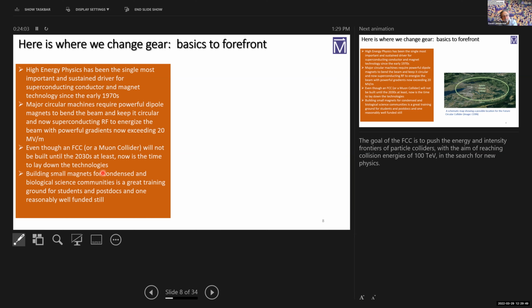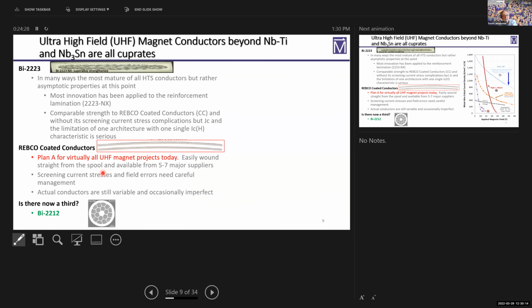And these magnets go up to 41 Tesla now as purely resistive magnets. And with a hybrid magnet of 11 Tesla of niobium-tin and 34 Tesla of copper, you get to 45.5 Tesla. So it's a great training ground. NSF definitely would like us to be able to replace more and more of these with superconducting magnets, and that's perhaps where the rest of my talk is.